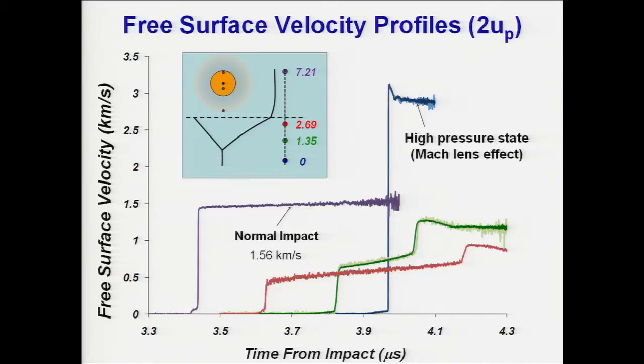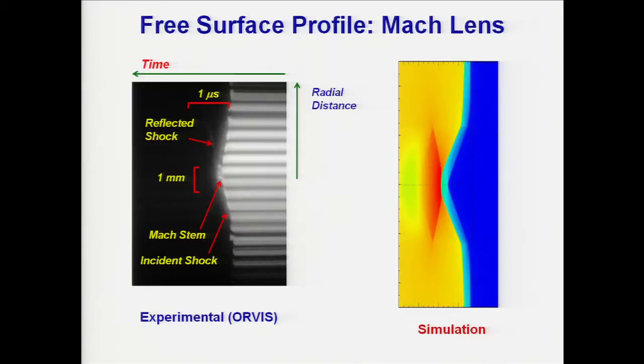And here are the probes at the back of the copper cylinder and also in the aluminum outer cylinder. Here you see that the free surface velocity reaches the impact velocity of 1.5 kilometers per second. But if you look at the center of the copper cylinder, where the Mach stem or the high pressure region is, then you get about twice the free surface velocity. So you've increased the particle velocity, and also the shock velocity corresponds to that of the outer cylinder. So we get these two enhancement effects. This way, we can enhance the pressure substantially.